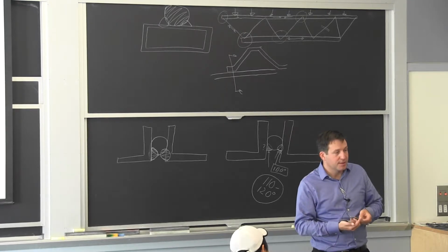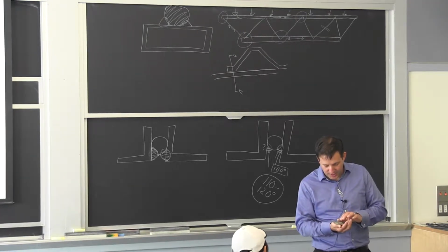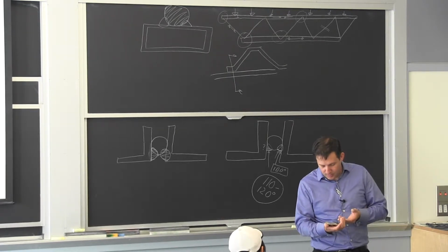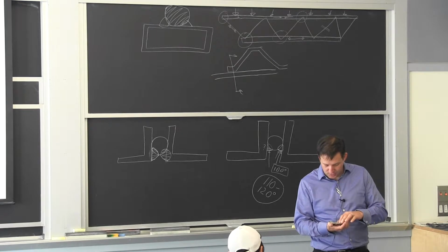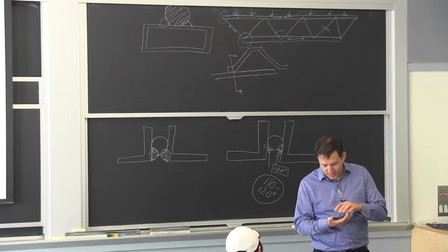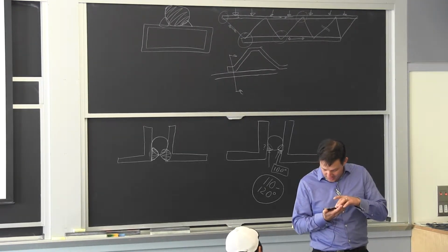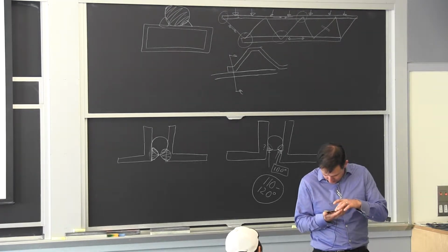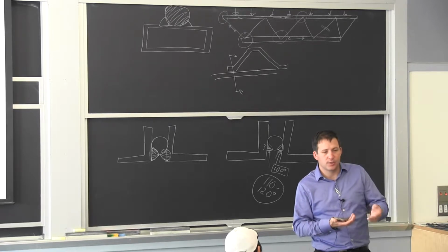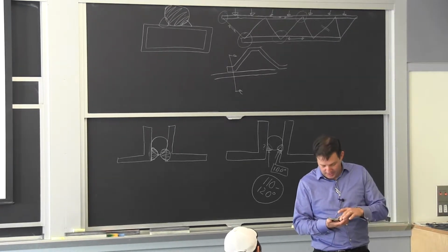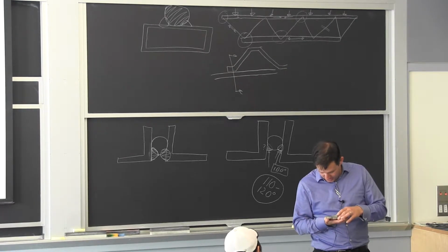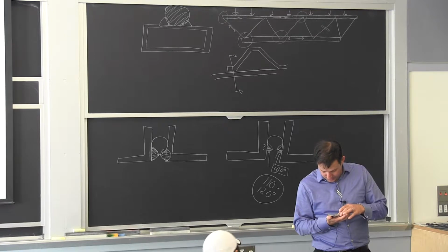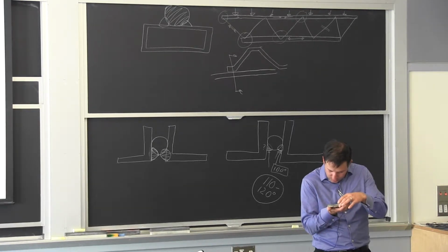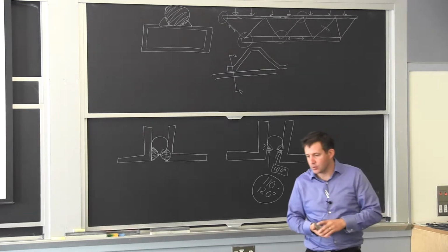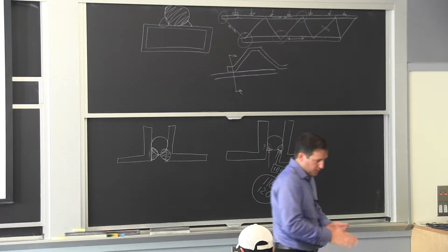and it's not a perfect joint. It's very rarely a perfect joint. Typically, you try to have 70% of the area where it's really bonded between one side and the other. And what you'll see in this joint is a lot of little cavities, and where on none of the sides you can see the solder, so you know it wasn't bonded. When it's shiny on these examples, normally it's when you didn't have enough, so you're only touching one side. It made this very nice surface. And the places that were really providing strength and also the seal resistance, they will look more dull because when it stretched and failed, it makes a dull surface here.